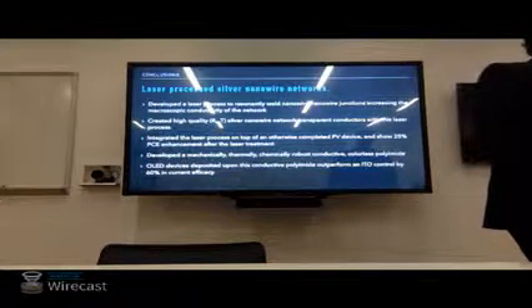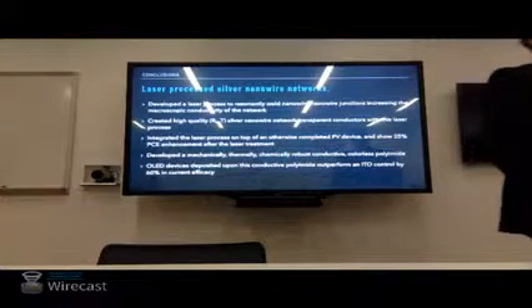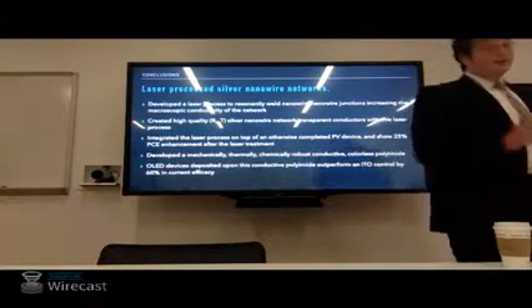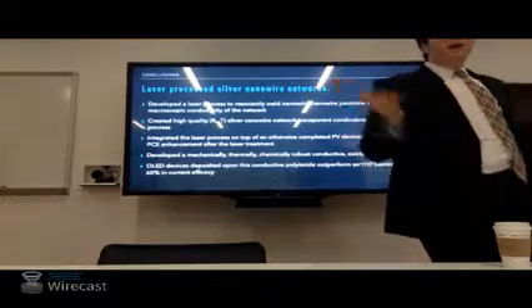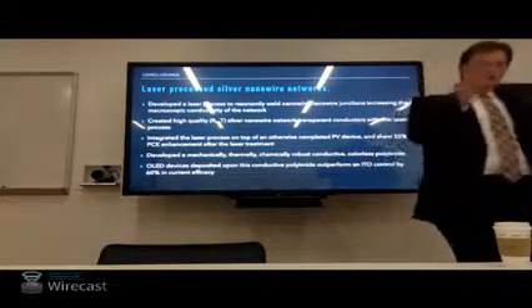What I meant there is that, in contrast to a planar contact, say a deposited silver film, the contact of a wire on top of a substrate is a line, right? So we could think of our surface energies as being altered. That really is what I blame for the adhesion issues, of why the nanowires don't adhere to anything. It doesn't really matter what substrate you start with in terms of surface energy, high or low, so hydrogen-terminated silicon or oxide-terminated silicon. It doesn't stick nicely on anything. And that's why these commercial companies have to add adhesives, probably organic molecules, to the inks.